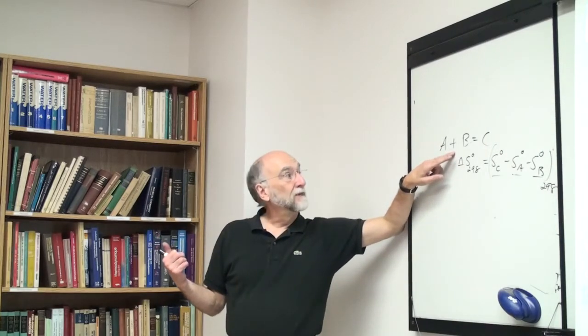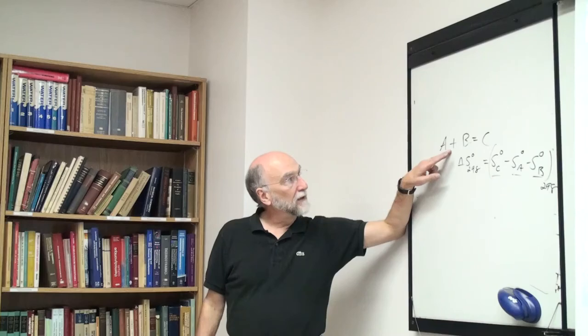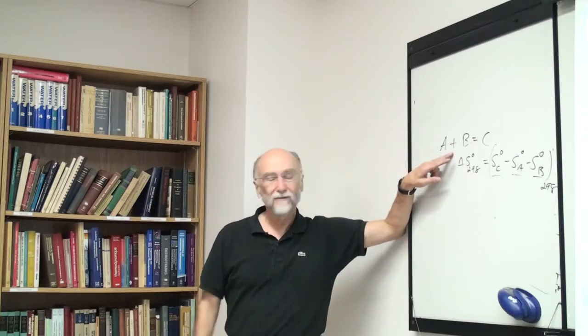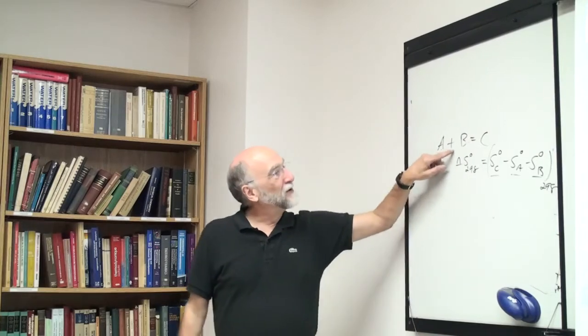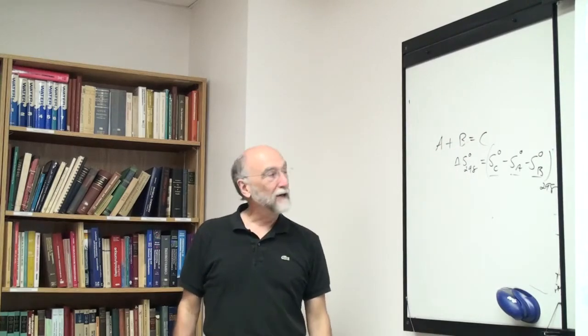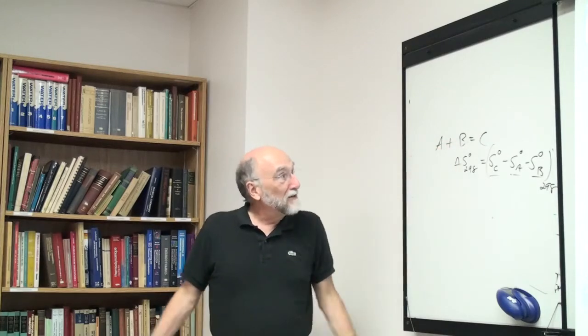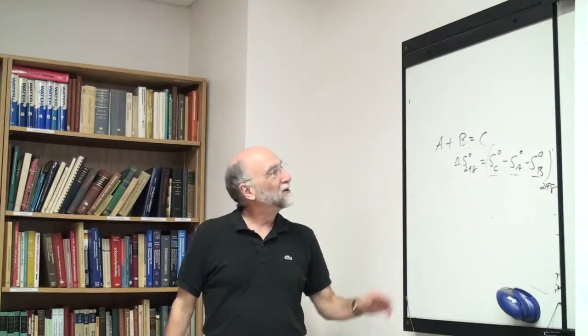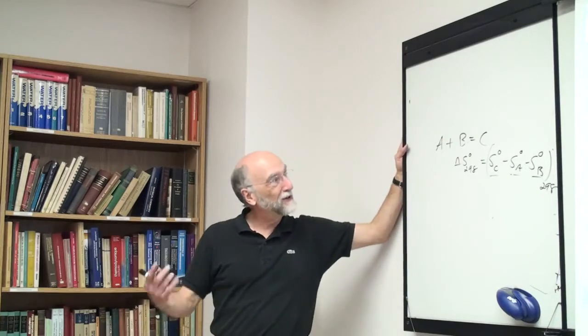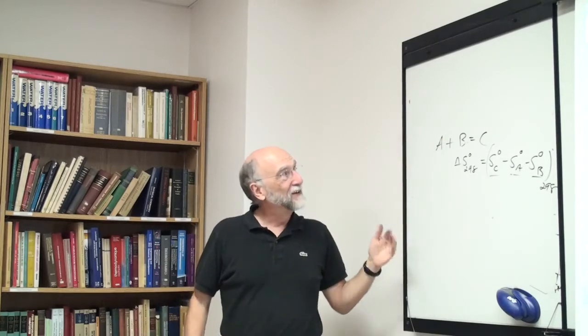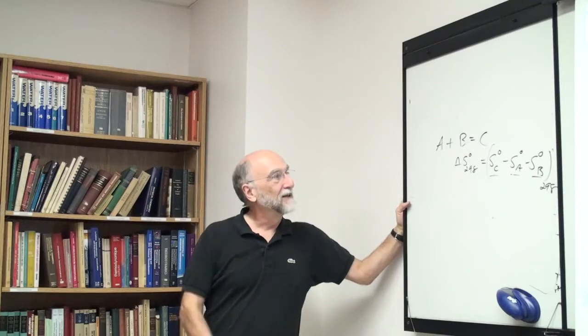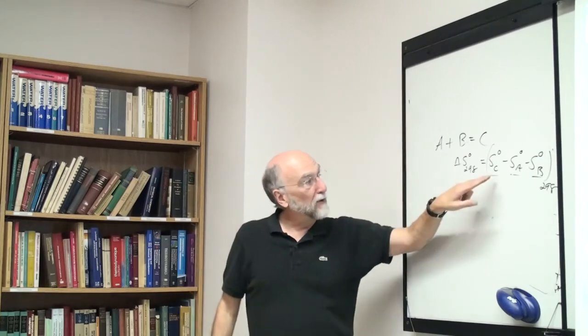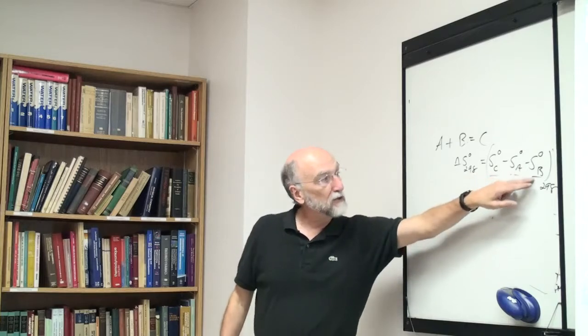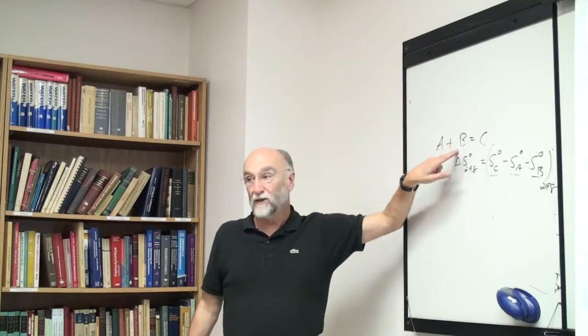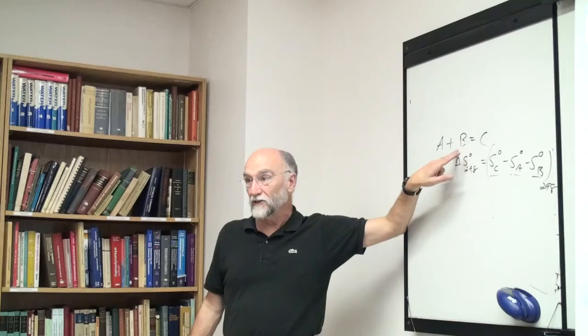And this is rather interesting because it means that I've obtained the entropy of this reaction without ever having the reaction occur, without ever putting A, B, and C together, without ever effecting the reaction. I can measure the entropy. What I do is I have three separate experiments, one on each pure material, and from that I obtain ΔS of the reaction without ever having the reaction take place.